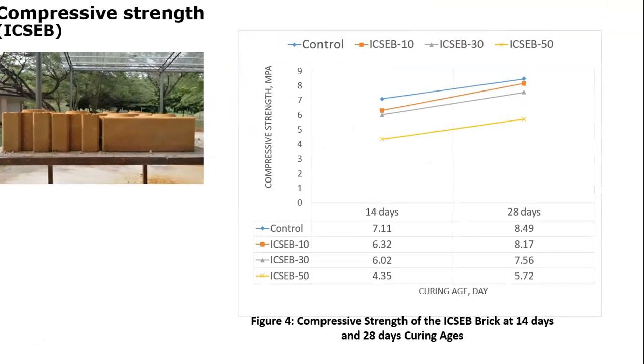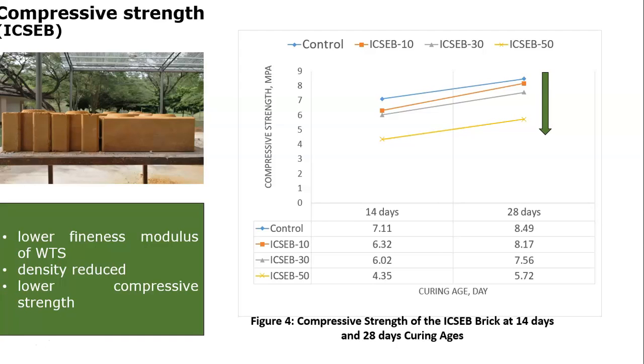A similar trend was also observed for ICSEB brick samples. Based on figure 4, it clearly shows that the compressive strength decreases as the percentage of sludge replacement increases. And this may be related to the microstructure of the ICSEB. The water treatment sludge has a lower fineness modulus, which is 2.45, compared to sand, which is 3.32.